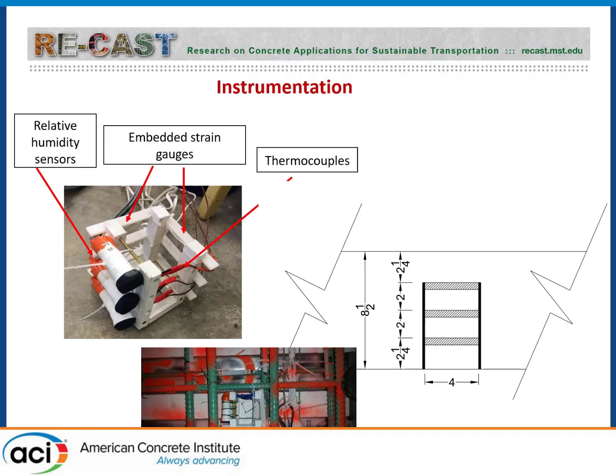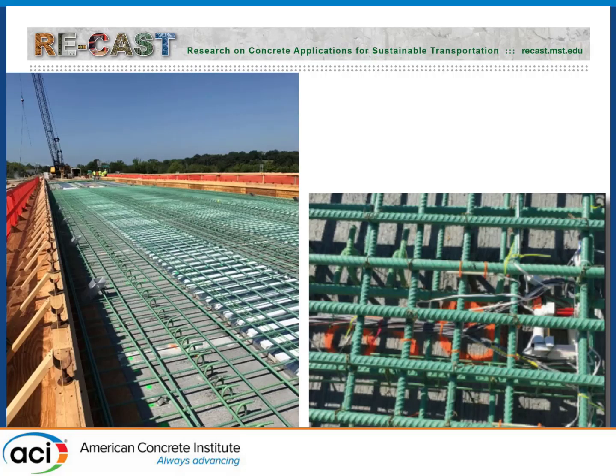And it was very important to do that. If you ever have to do this, do that as a last stage before construction starts, before concreting. So they basically gave us about 6-7 hours. There were like 240 wires that had to be connected from the bridge deck all the way to the data acquisition system, and we were almost concreting at the same time as we were installing the sensors. Because if you do that ahead of time, often they get broken down from construction traffic.